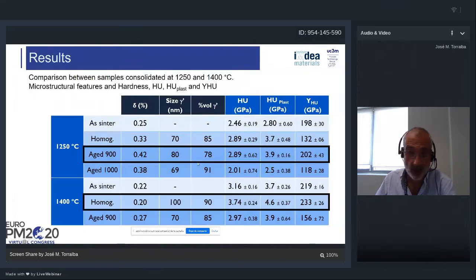Here we can compare all the results. In that case, we have the best mechanical properties for the higher value of the misfit, but it's not the same for the 1400 degrees, maybe due to this strange microstructure with those channels for the gamma matrix. We should perform some tests at higher temperature in order to check how the misfit really affects the high temperature properties.